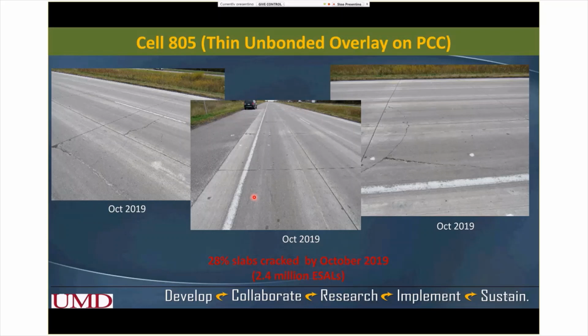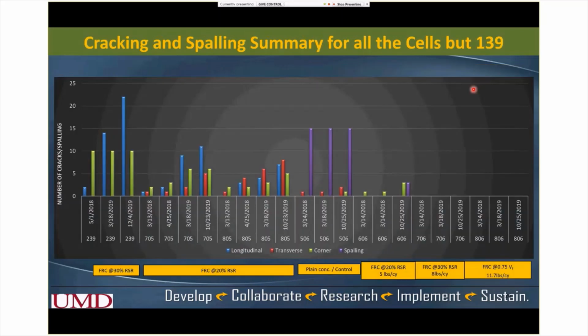Now this slide shows a comparison of the fatigue cracks and spalling. We can see cell 239, which was 4-inch thick with a little weak base, showed the maximum number of cracks. We did not include cell 139 in this comparison, because 139 really showed a different kind of failure, like slab shattering, and counting the cracks in that cell was difficult. And as we know that 75% of the slabs in that cell cracked, we did not consider cell 139 in this comparison.